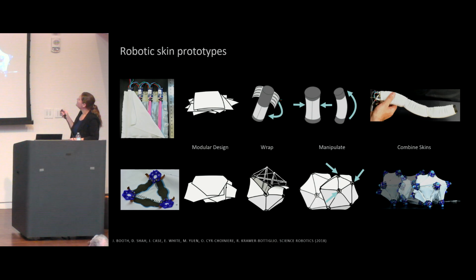And then attaching a few of these together. So here, this is a long tube of foam, and we've taken 3 rectangular robotic skins and just put them all together in parallel. And you can see this kind of multi-segment soft continuum arm. So then a second embodiment that we created of the robotic skins uses a different substrate. So instead of an elastomer substrate, we went to a fabric substrate.